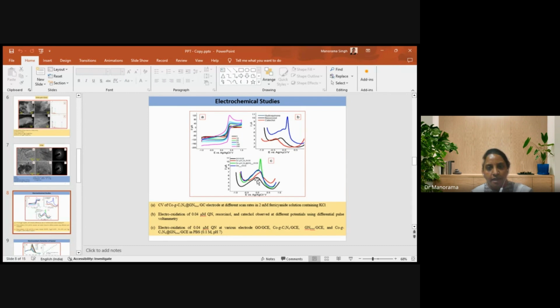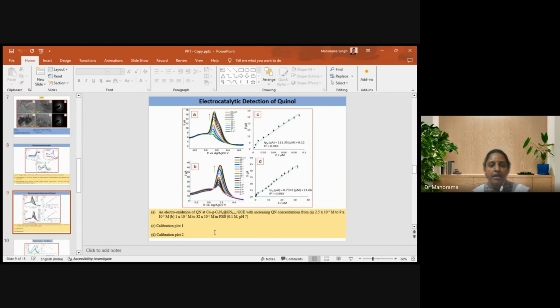So further, we have studied with the different modified electrodes at each step. With the only graphene oxide modified glassy carbon electrode, and cobalt doped graphitic carbon nitride modified glassy carbon electrode, and the graphene nanosheet modified glassy carbon electrode, and cobalt doped graphitic carbon nitride at graphene nanosheet modified glassy carbon electrode, in phosphate buffer solution 0.1 molar pH 7. So we found that the maximum current we found at the final nanomaterial which we have prepared when we modify the glassy carbon electrode.